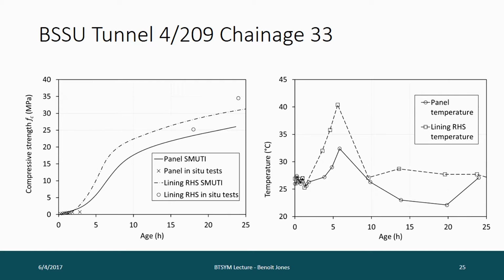And you can see the lining has gained strength much more quickly, and that's because if you look on the right, the temperature history is different for the lining, and the temperature is warmer. And I should note, while we're talking about temperature, that we're measuring the surface temperature, and actually within the thickness of the shotcrete it's probably warmer than it is on the surface, because the surface is cooled by the air. But even so, we typically get peak temperatures of 40, 50 degrees quite often, even on the surface. So it's quite a big change in temperature we're measuring. I think that just sort of proves what's going on.